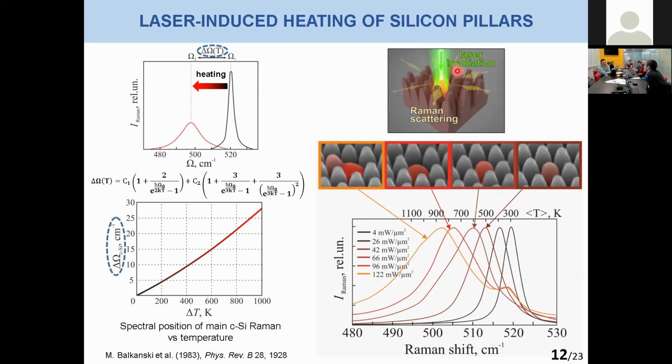But still, before coming back to your first question, to make it clear, what Gosha asked: will the Raman intensity increase 4 times when I increase the pump intensity 2 times? No, it will increase 2 times. Yes, thank you, Misha. But if you somehow increase the field enhancement factor 2 times, then your SERS signal will be enhanced 4 times. Yes, so it's linear. It's a good question to make it clear.